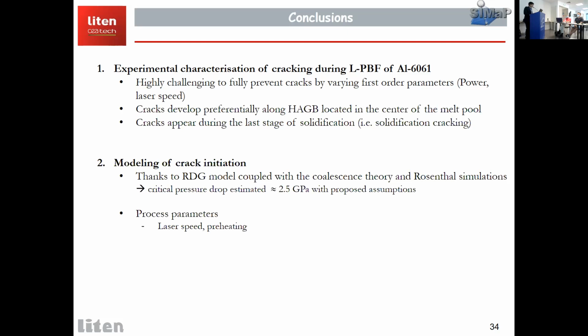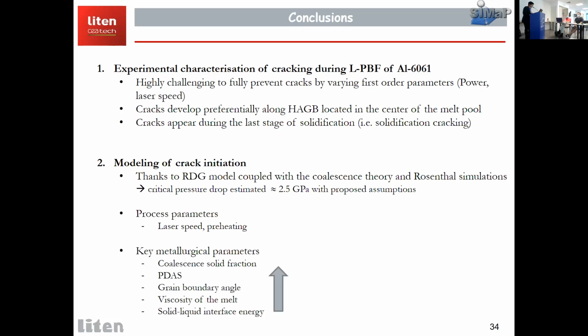We also identified which are the processing parameters which are key to reducing this pressure drop. For example, we need to go to low laser speeds. We need to implement high preheating temperatures, for instance. In our study, we also identified key metallurgical parameters. For example, the coalescence solid fraction, the primary dendrite arm spacing, the misorientation aspect of the microstructure, the viscosity, the solid liquid interface energy. So these are the parameters which we have identified.